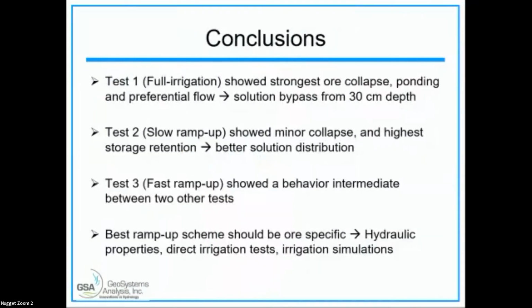Next. So in conclusion, test 1 with full irrigation showed the strongest ore collapse, promoting preferential flow below 30 centimeters of depth. Test 2, minor collapse, highest storage retention, better solution distribution. Test 3 showed an intermediate behavior. And just as a general comment, Dr. Mike Yao had a paper yesterday where he talks about some of the other test work we've been developing to look at this problem. Your best ramp up scheme should be ore specific. And you need to take a look at the hydraulic properties, do some collapse tests, and simulations will help you.